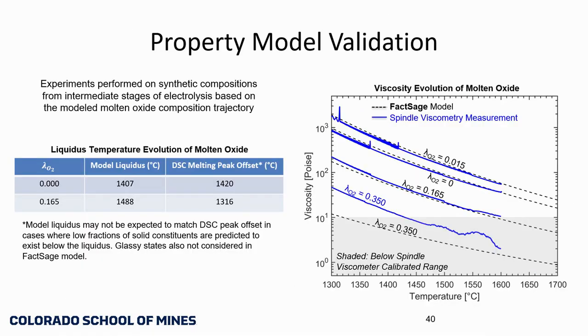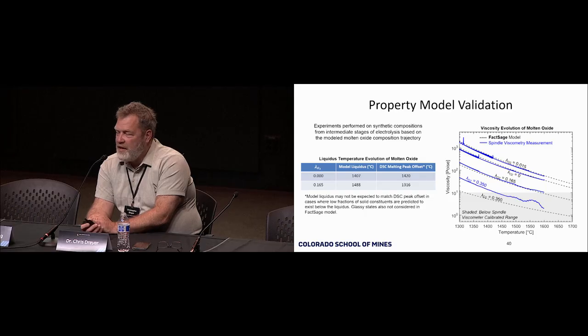We've also done, as I mentioned already, viscosity calculations from FactSage. We've also looked at that in a couple other ways. We've directly measured the melt and molten regolith viscosity at Mines. We have another paper coming out that's going to focus on this with different melts and different reduced oxides.